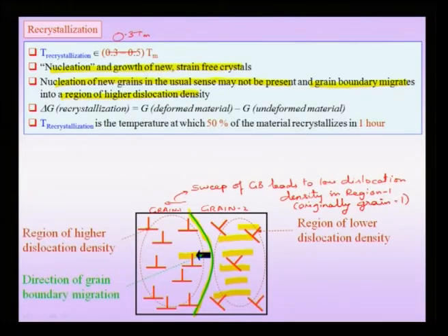So the region which was originally grain 1 will have a reduced dislocation density. Of course, we may have formation of new strain free crystals which may grow, which also leads to a reduced dislocation density. And of course, the driving force for this process is the fact that the free energy of the deformed crystal is higher than the free energy of the undeformed material, and therefore you have a free energy benefit when the material comes down to a low energy state.